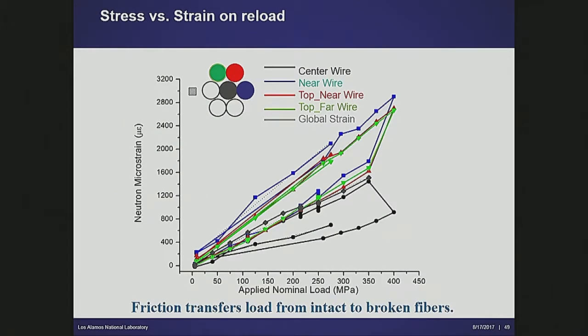Now, in this graph, when you unload, let's say that you got to an applied stress of somewhere between 350 and 400 MPa, you can see all these coming back down to 0 as you take the load off. But here's the interesting thing. When you load it up again on the next cycle, this strand that was broken doesn't follow the original line, but it does take load here. And these other strands come up a different line here. This reflects the fact that in this particular location you could make measurements in the broken cable and surrounding cables.